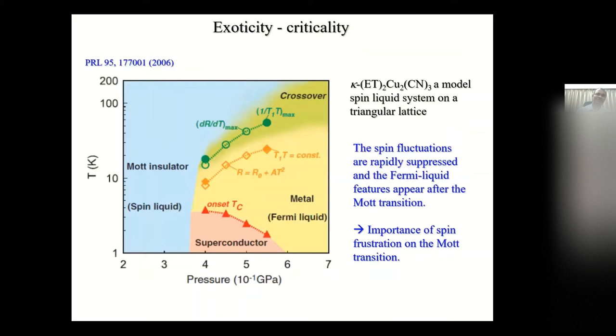You can also have organic superconductors — somewhat different from the previous cases. In the heavy fermion and cuprate cases, electron correlations are very strong and the ground state is magnetically ordered. But in this organic material, there is no magnetic order — there is a spin-liquid phase separated by a phase boundary. Going from that phase to a high-pressure regime you can get a Fermi-liquid metal, and at sufficiently low temperatures you can achieve superconductivity. The most recent thrust area is iron-based superconductors, which I'll be primarily discussing today.